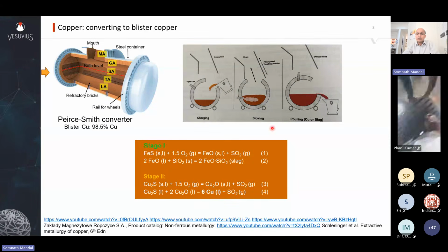And then sometimes they skim out the slag and blow again, and sometimes it's a continuous process. What you get out of here is blister copper, which is about 98.5% purity. It's called blister because if you take this copper and solidify it, it will tend to have blisters in it. Anyway, this 98.5% copper is still not done yet.